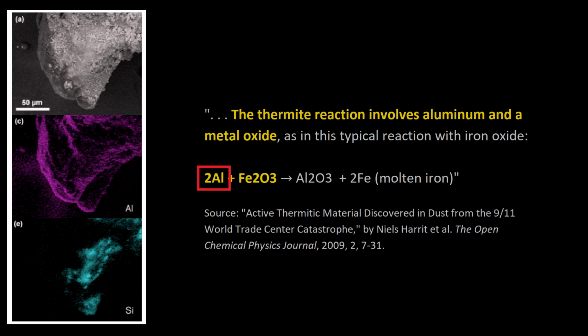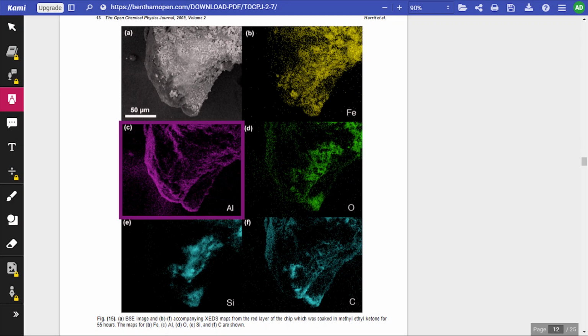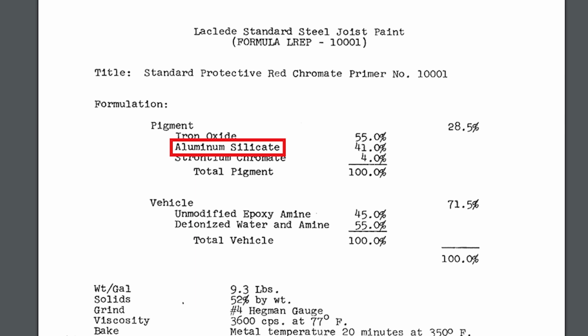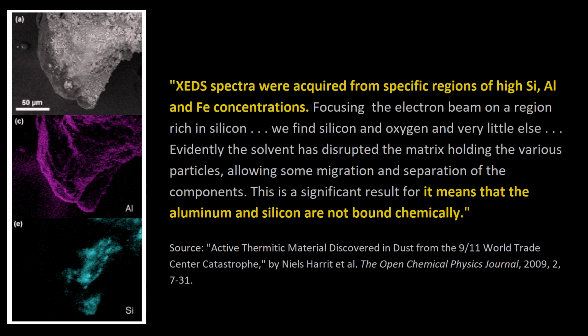What about the elemental aluminum? This appears to be the kicker here, because while it's not made clear in the paper, presumably one would only expect aluminum to be present in combination with other elements that it's chemically bound to, such as aluminum silicate in the form of the kaolin pigment that was used in the primer paint. Indeed, they write in the paper, quote, XEDS spectra were acquired from specific regions of high silicon, aluminum, and iron concentrations. Focusing the electron beam on a region rich in silicon, we find silicon and oxygen and very little else. Evidently, the solvent has disrupted the matrix holding the various particles, allowing some migration and separation of the components. This is a significant result, for it means that the aluminum and silicon are not bound chemically, end quote.